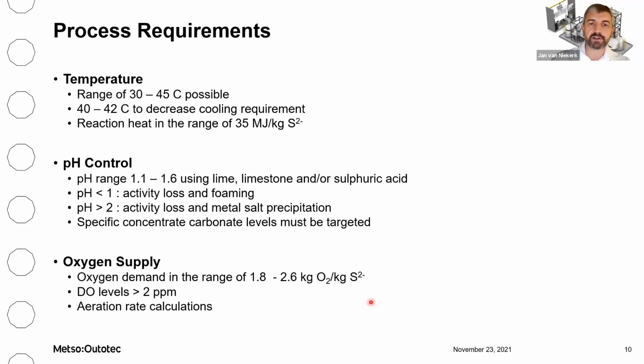Probably the biggest operating cost and engineering requirement during the operation and design of a BIOX tank is the supply of oxygen. You require in the order of 2 kilograms of oxygen per kilogram of sulfur oxidized. And as we are supplying the oxygen in the form of low pressure air, it will mean that a large volume of air is pumped into the reactors. And the agitator needs to be able to disperse that air and also drive the oxygen mass transfer from the gas phase through the liquid phase to the mineral sulfide interface.